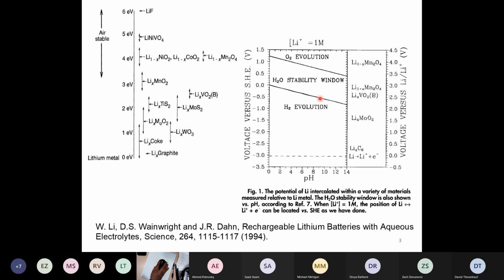When you look at this, you say, well, there are some materials that maybe we can make a water-based lithium-ion cell out of. In our work in this early paper, we picked VO2 for the negative electrode and lithium manganese oxide spinel as the positive. If you work at very high pH, you'll have oxygen evolution problems with the positive electrode. If you work at acidic pH, you'll have problems with hydrogen evolution at the vanadium oxide electrode. So maybe somewhere around neutral pH, you can get something that works. That was the idea.